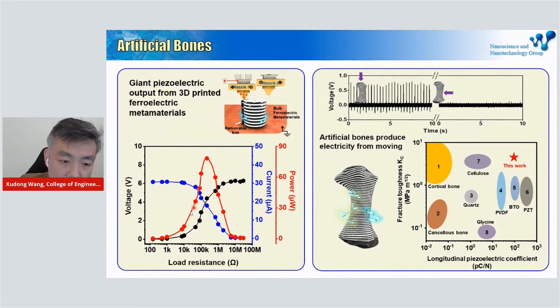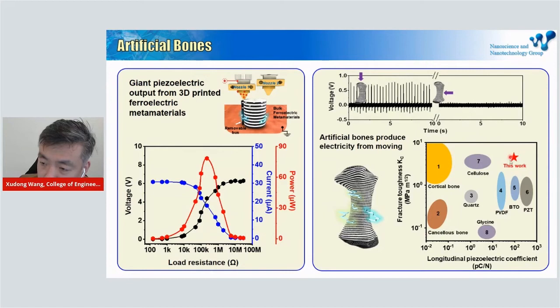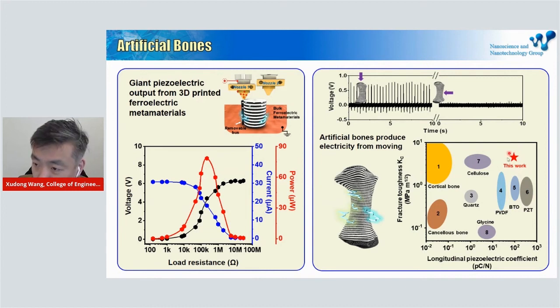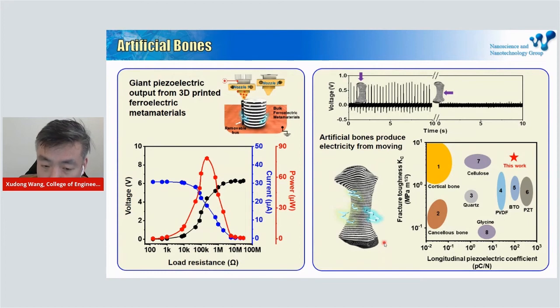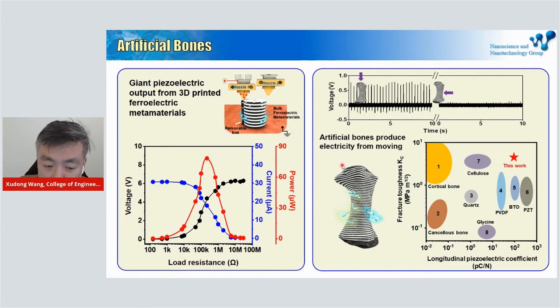A single stack of our material can produce electrical power up to 80 microwatts from one piece. From this chart, we can see our material sits in the top right corner, meaning it has the same toughness as real bones as well as a high electric output comparable to many other ceramic materials. Our printed bone structure is as strong as a real bone and can also generate an appreciable amount of electricity when pressed, opening many opportunities for human-powered devices or even robotic systems.